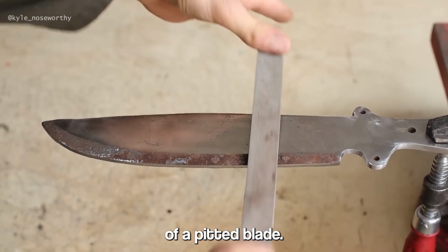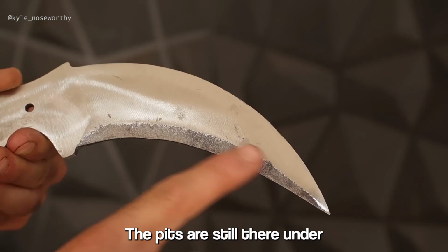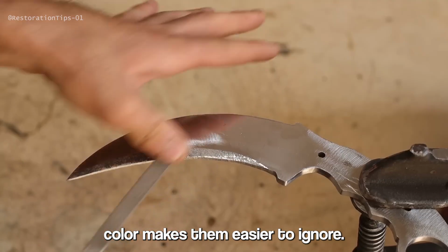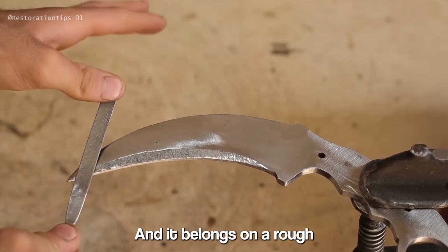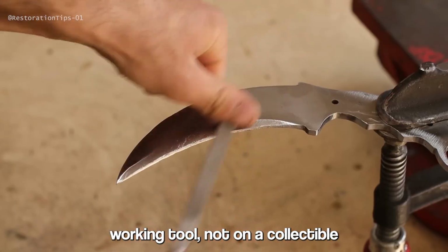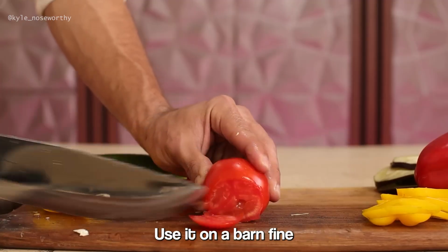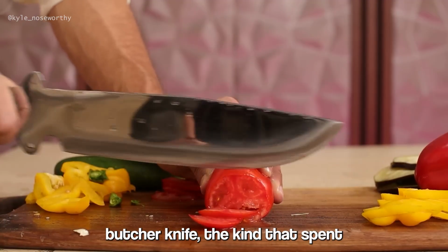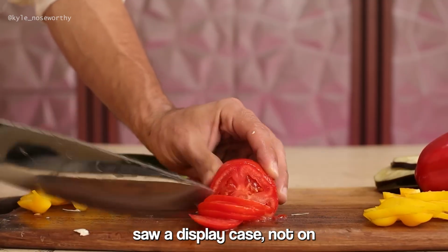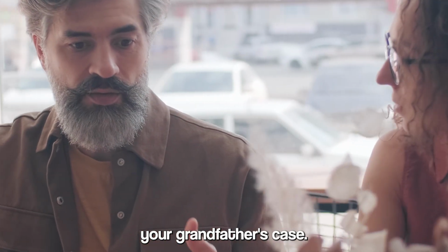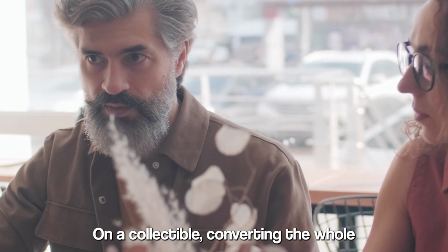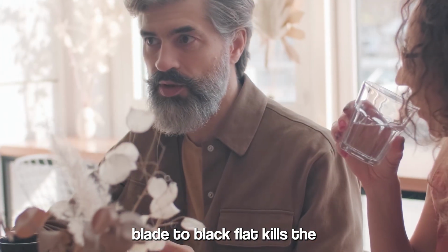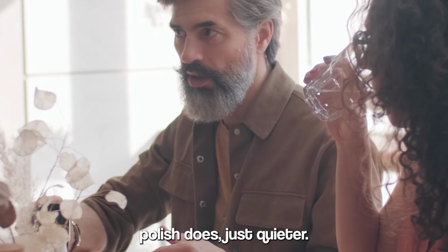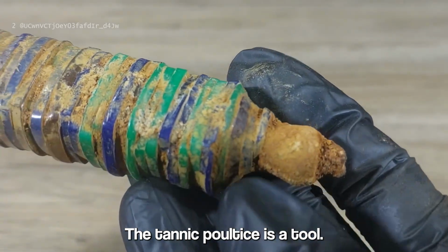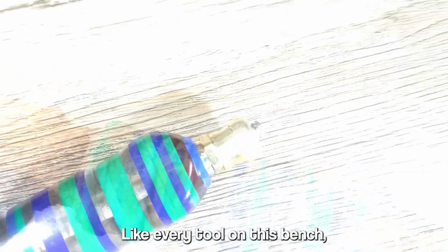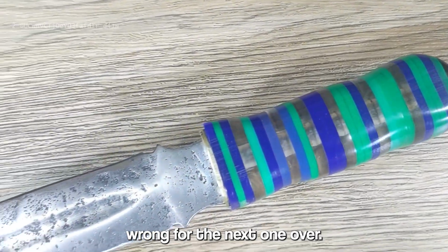It does nothing for the shape of a pitted blade. The pits are still there under the black, and if anything, the color makes them easier to ignore, and it belongs on a rough working tool, not on a collectible you'd rather see cleaned properly. Use it on a barn-find butcher knife, the kind that spent 40 years cutting hog and never saw a display case, not on your grandfather's Case. On a collectible, converting the whole blade to black flat kills the value the same way a mirror polish does, just quieter. The tannic poultice is a tool. Like every tool on this bench, it's right for one job and wrong for the next one over.